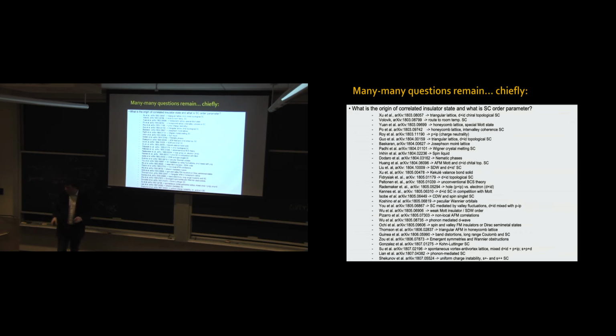I come from graphene and 2D materials physics, where I always tell people that the angular cone of disagreement between theorists is about 20 degrees, more or less. So if you look at this list of papers, the angular cone of disagreement is 2 pi. In fact, it's actually 4 pi. It's no directions. So to me, this is something a little bit new, to find that there's so much disagreement. People have predicted all kinds of orders, all kinds of S, P, D, S plus P plus D plus F, all letters of the alphabet, for the order parameter.